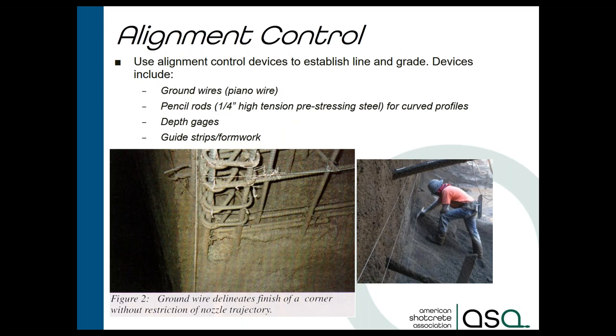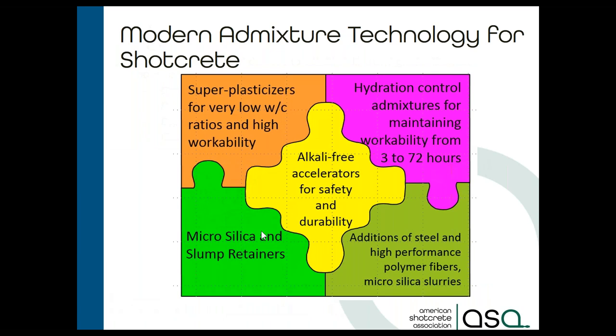Alignment control — you saw the skate parks and the luge run — we can meet very tight tolerances. Pretty common to use shooting wires or ground wires, high-strength wires that establish, for example, the corner of a wall. We shotcrete to that wire, cut the material to that wire, and know that we have the proper cover over the reinforcing steel. Shotcrete is one of the most sophisticated users of concrete out there today. We use superplasticizers to get a very low water-cement ratio. Water-cement ratios are typically from 0.3 to about 0.42 with wet mix; dry mix tends to have a lower water-cement ratio. We use alkali-free accelerators — rapid-set accelerators that allow us to get strength very early.